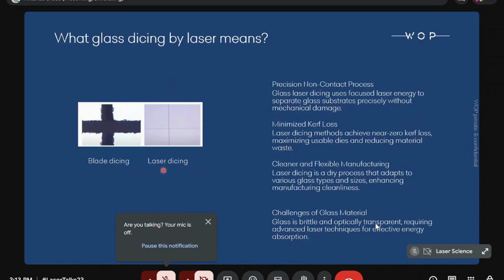Meanwhile, laser dicing. I have to mention that both these photographs are made with the same magnification. So you can see that it is much more precise and clean. As it is a non-contact process, there's no contamination with debris. It's clean and flexible manufacturing. As you can see, it is very, very little kerf, meaning you almost lose no material. But of course, if you deal with glass, you have to be careful, taking into account glass material features.